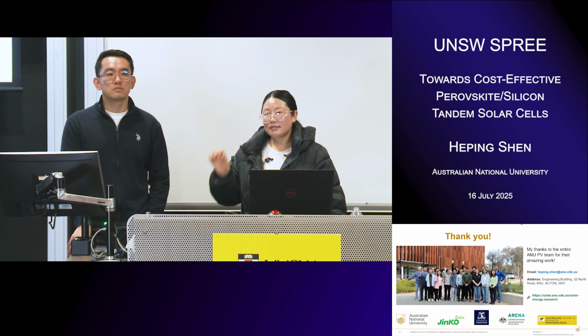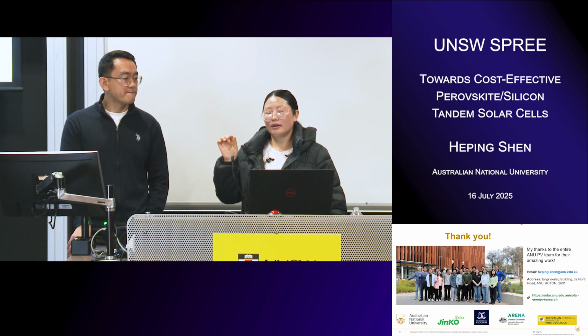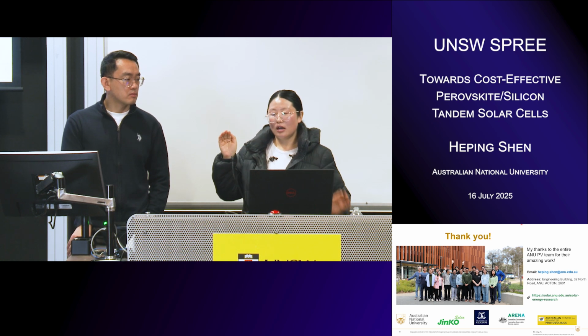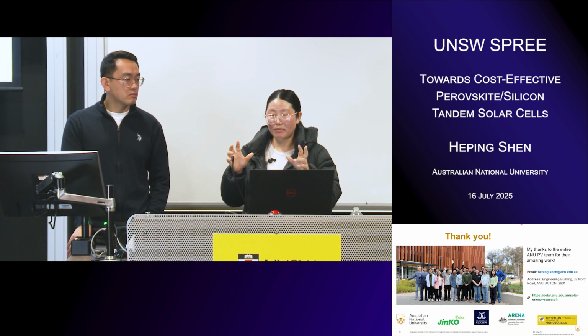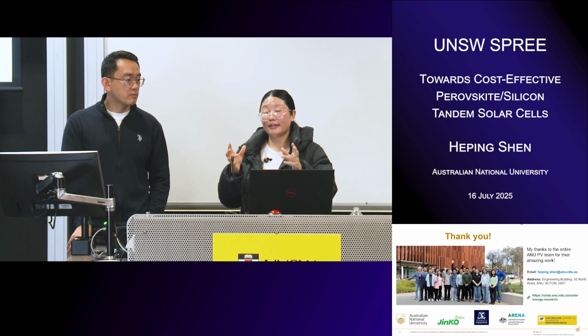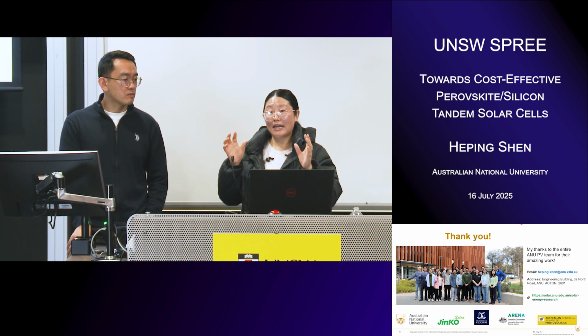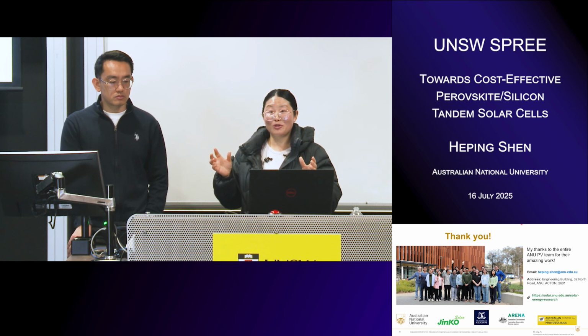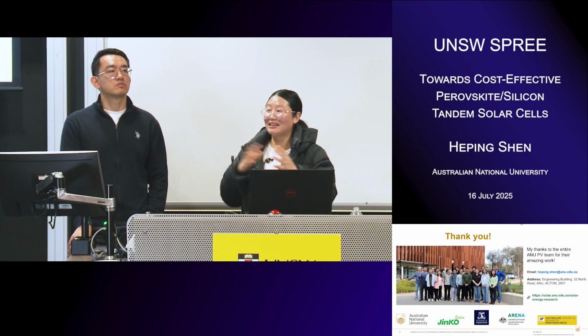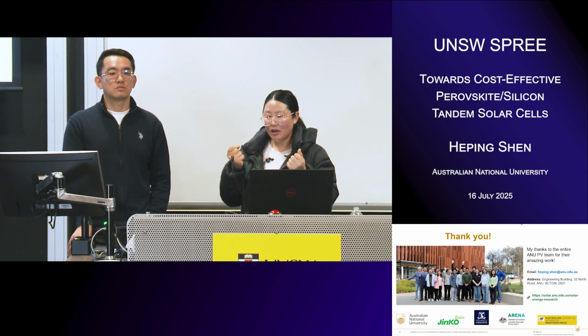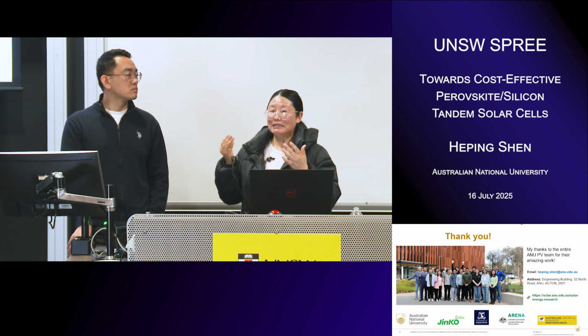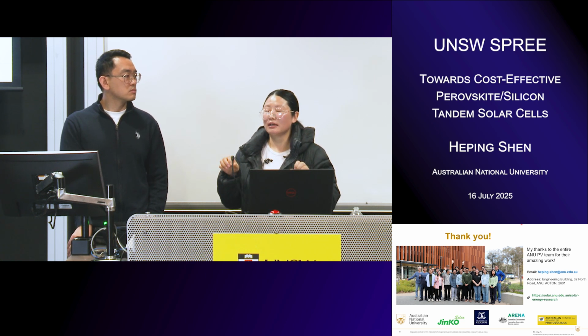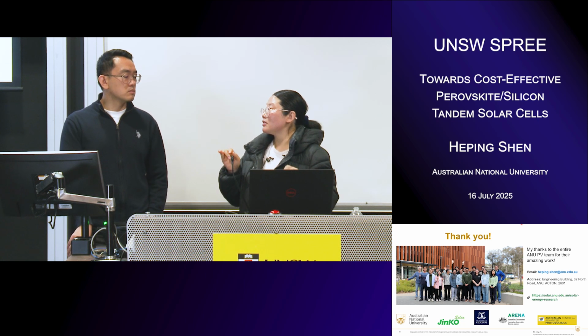And second is that I mentioned the scalability. So particularly for that structure, you can see here, for the TCO layer, for example, for tunnel junction, whatever we make, they are relatively highly conductive laterally. That means if there are any pinholes in this layer, that will become the source for the shunting. And unfortunately for this TCO layer, or the tunnel junction, if you have fabrication experience in the lab, you will find that sputtering-deposited TCO will very possibly have this shunting and these pinholes. It won't be very complete like ALD. So possibly, I think we will be having some challenge.